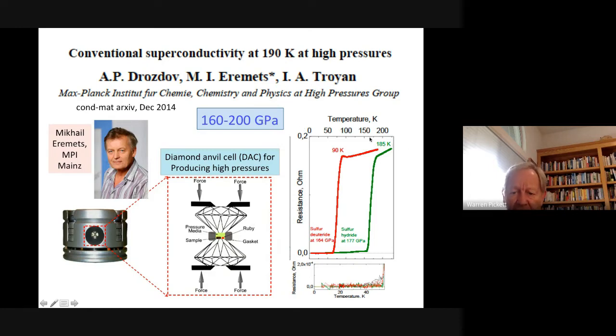And this is just showing for hydrogen 3 sulfur. This sample became superconducting at 185 Kelvin. That's the onset here, at a pressure of 177 gigapascal. This is another sample, which is not hydrogen, but it's deuterium. So it's twice as heavy as hydrogen, but otherwise it's the same. But it changes the hydrogen frequencies by a factor of square root of 2.